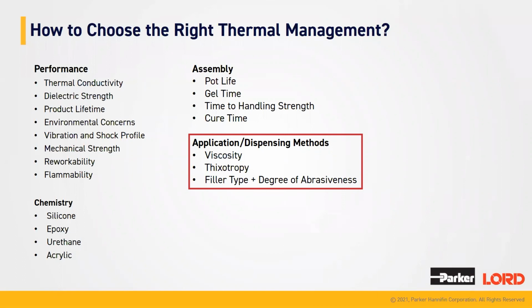Things to consider. Thixotropy, we talked about this before too. Do you need something that once it's dispensed, it will never move and it can be vertical against a 90-degree surface, or does it need to be able to flow freely? And then finally, filler type and degree of abrasiveness. This is something that's been really popular as thermal management has become more popular because filler is required to add thermal conductivity. But as a result, you're adding these solid particles that can be damaging to the equipment. So you have to make sure that the equipment is designed properly for the right material that you're using.